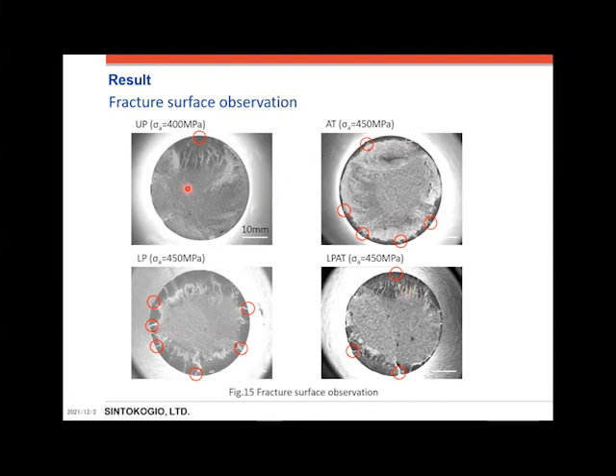This figure shows the fracture surface observation. The upper side of the figure shows each condition and the stress amplitude value. In addition, red circles in the figure indicate crack initiation points. In all conditions, the fracture initiation point was from the surface. However, in the LP, AT, and LP-AT conditions, several surface crack initiation points were found.